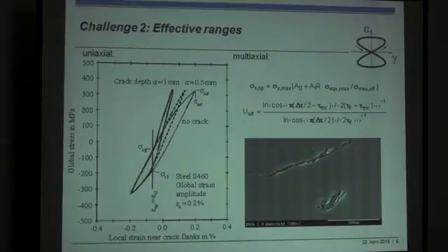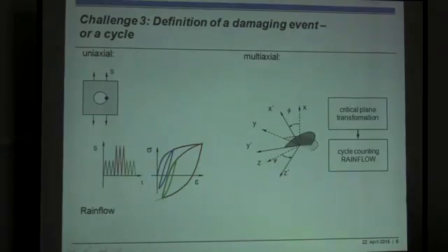And for the mode 2 and mode 3 portions of the cyclic loading, we reinvented some efficiency ratios with a more or less complicated formula, taking a threshold of friction into account and adding another material parameter which must be identified and makes the application a bit complicated, but these equations are now available, and this is what we use. And I do not want to go in much more detail today.